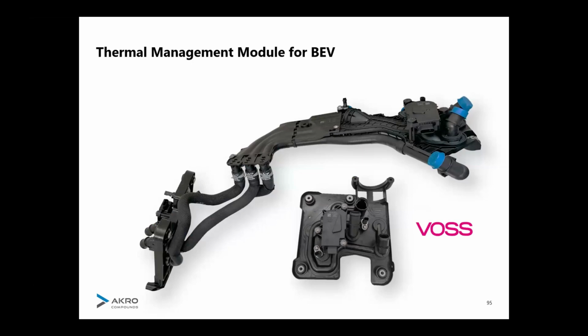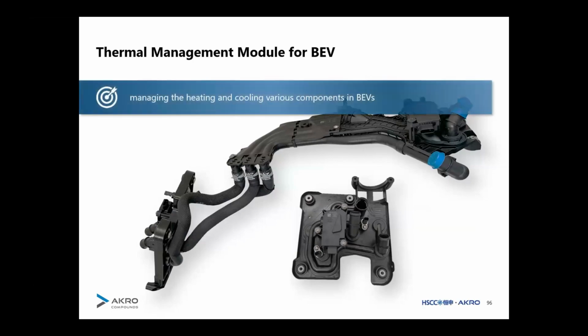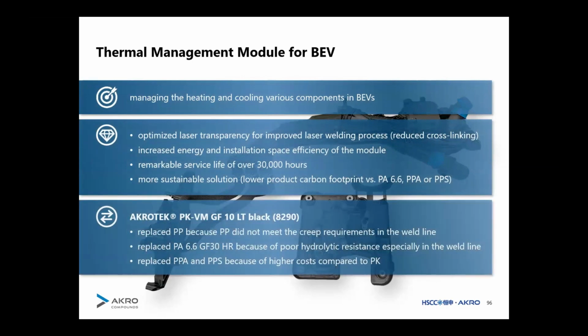Similar application also for the PPE platform, the Premium Platform Electric from the VW group, from the company Voss. And here they use a laser transparent grade because it has an easier geometry, and you can go with laser transmission welding. And you see, the special thing about this grade, as indicated by LT for laser transparent, is that you have improved laser transparency. We also have a stabilized material and can maintain a very good laser transparency even after the injection molding process.